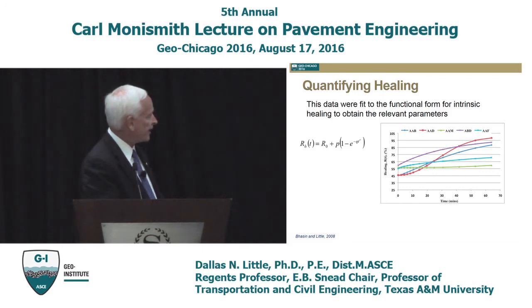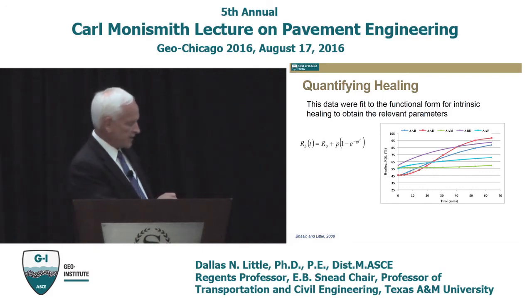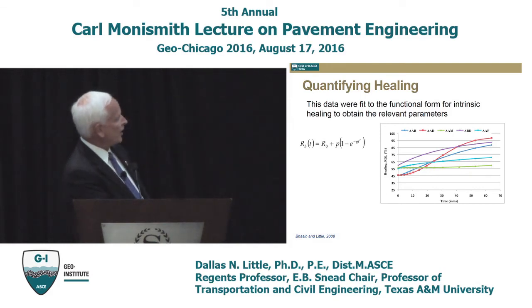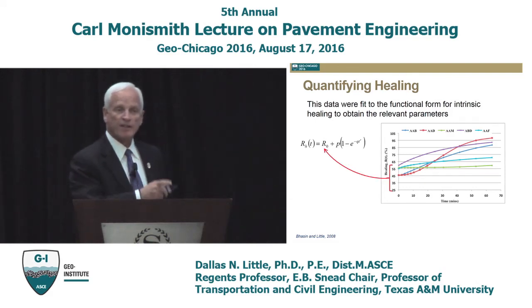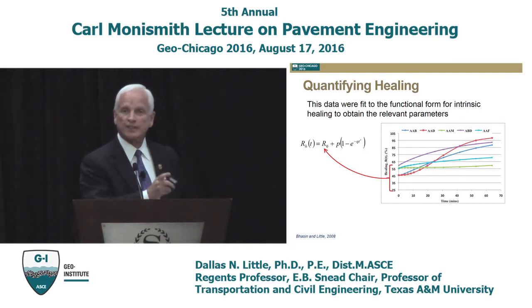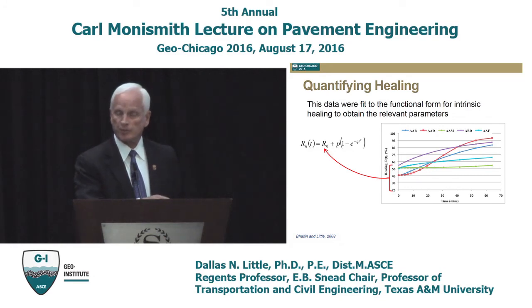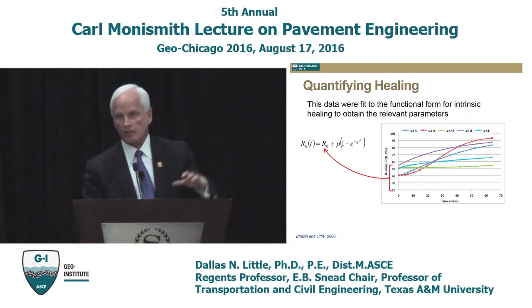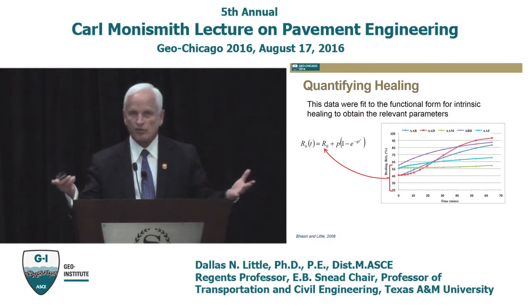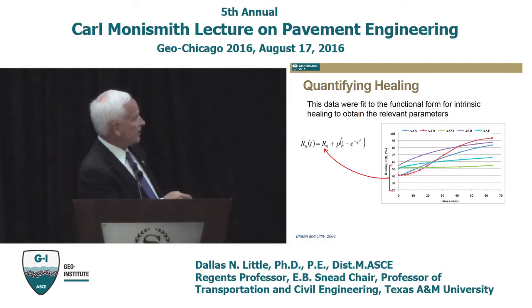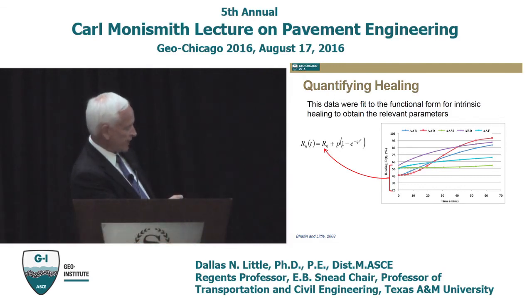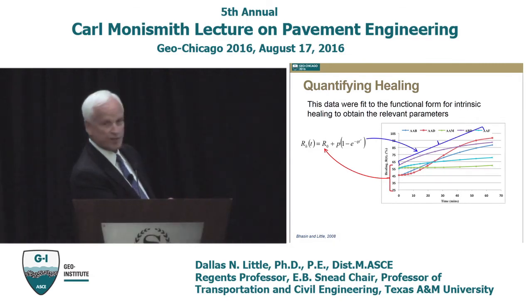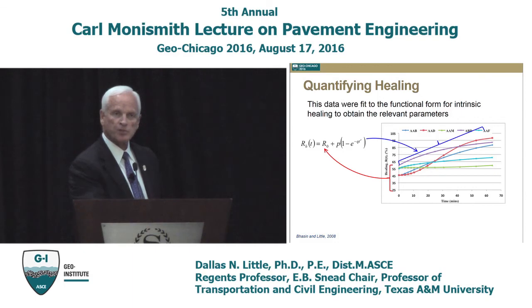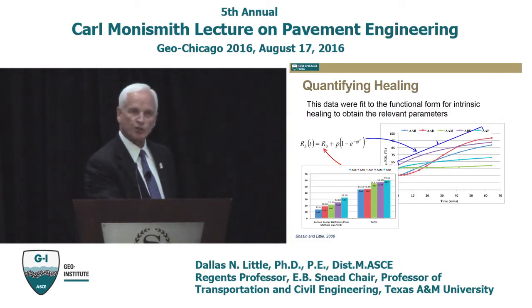So we did some more research in that area, and sure enough, what we found was that if we were to correlate this R sub 0 term for these 5 asphalts, by the way, they represent 5 very compositionally different asphalts from the SHRP Strategic Highway Research Program. Some heavy in asphaltenes, some heavy in maltenes, some heavy in saturates and so forth. They're very different. And we also track those by measuring the surface free energy of those 5. And they rank, although there's not a lot of difference here, you can question the statistics here, but they rank right along with that R sub 0 term. The higher the free energy, the greater the initial wetting.